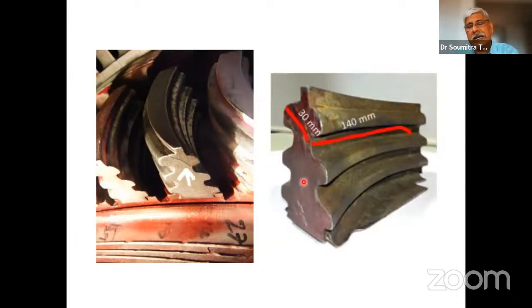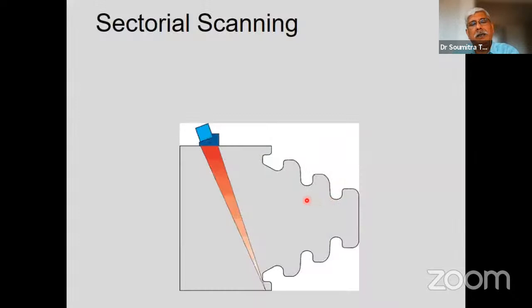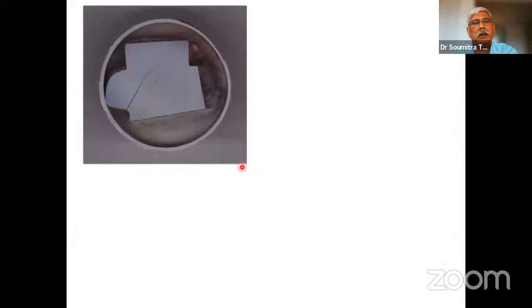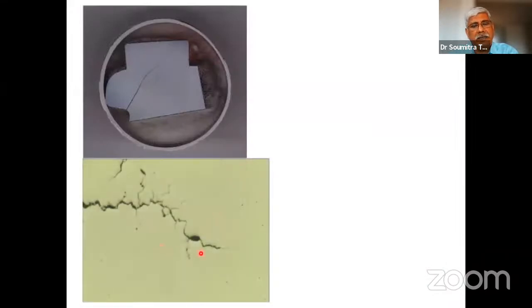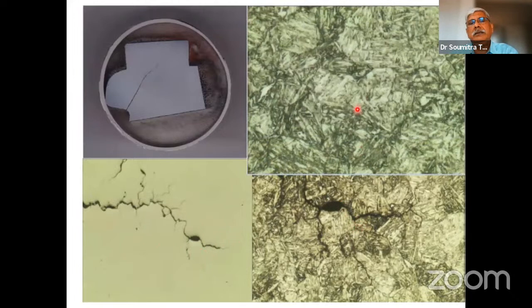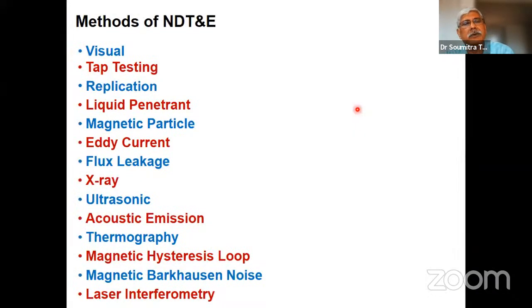So we analyzed that crack and from where it came. These types of defects could be ultrasonically identified and located through these types of NDT techniques, ultrasonic techniques, to which I'll come later. The sectoral scanning technique using phased array techniques. So we looked at the crack, the microstructure of the welded material after post-weld heat treatment to make sure that it is accepted. So these were some of the work that was carried out.